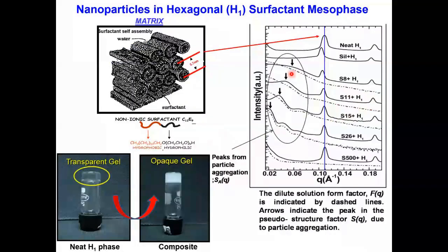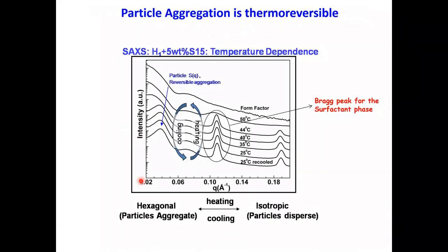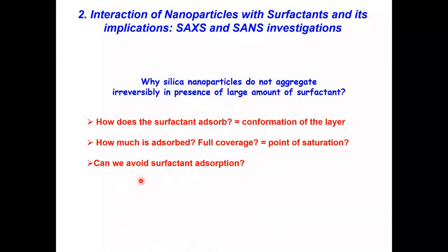What I would like to say is that this entire aggregation of the particles, going from transparent to opaque, is reversible in nature. You take the system to higher temperature, the surfactant system melts, and the particles separate out. But if I cool the system down, the particles again aggregate and form the opaque structure.